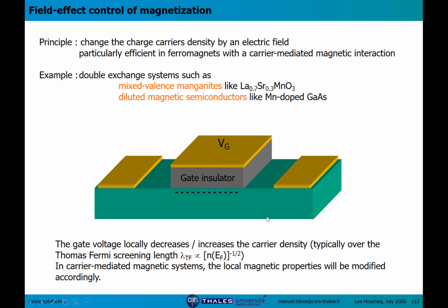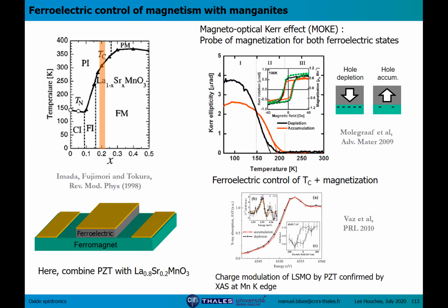So ideally, you want to use material with carrier-mediated magnetism, such as manganese-doped gallium arsenide or manganite, which are double exchange ferromagnets. And you want it to be very thin, because the accumulation or depletion of charges, as I've mentioned before, is only going to occur over typically the Thomas-Fermi screening length, which is at most a few nanometers. So there's a number of results in the literature using manganites.